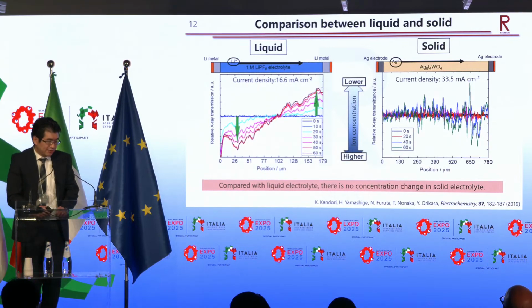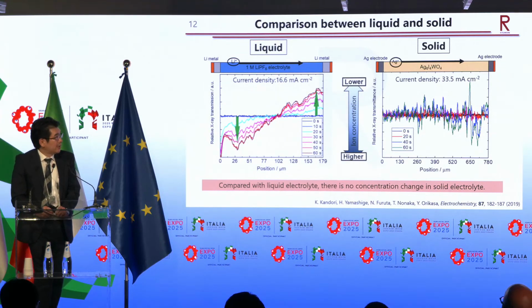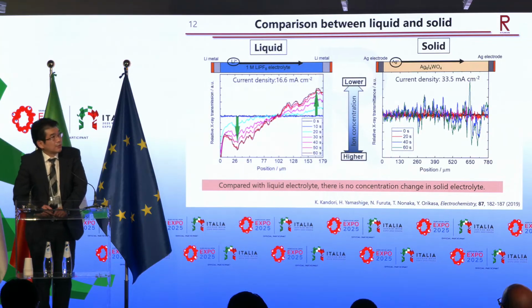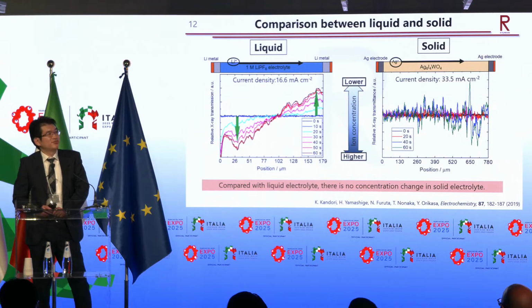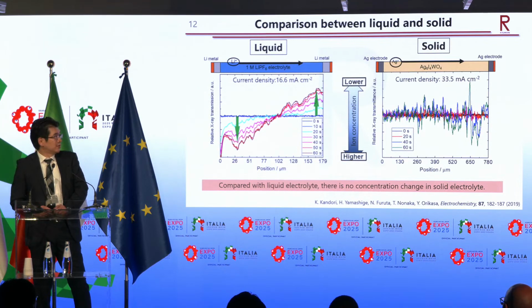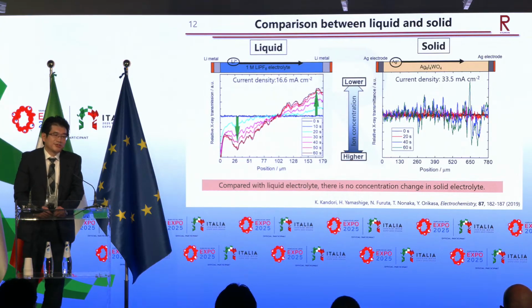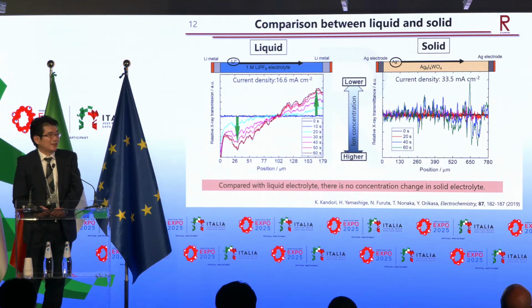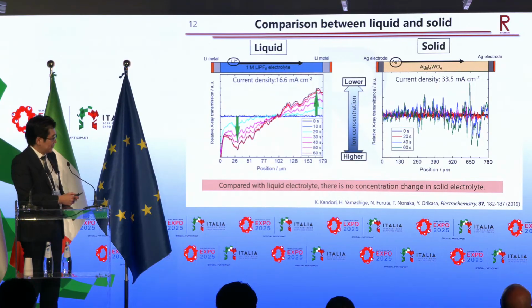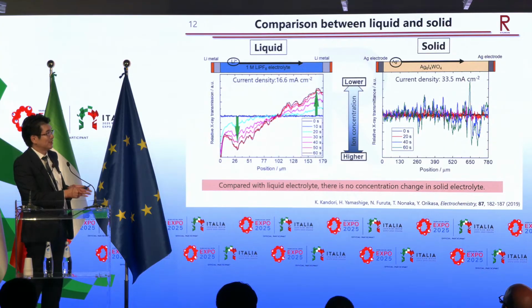So when using the all solid state battery, the concentration of the ion is almost constant during charge discharge. This is very, very important for the application of all solid state battery, because the concentration distribution is one of the disadvantages, and it limits the high rate charge discharge of the lithium-ion battery. So after this finding, we know all solid state battery possibly exceeds the charge rate capability of lithium-ion battery. This difference is based on the transport number of ion of the electrolyte.